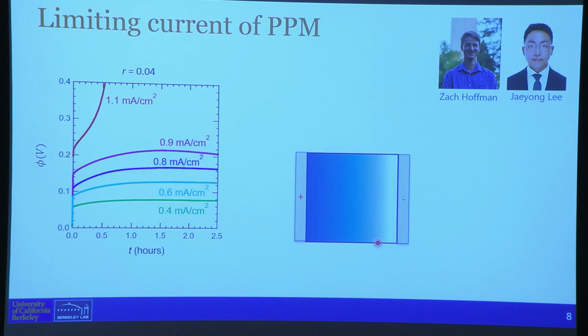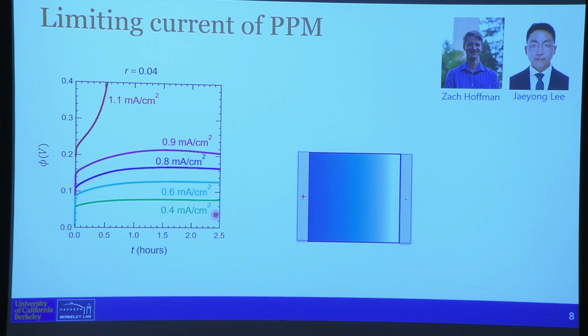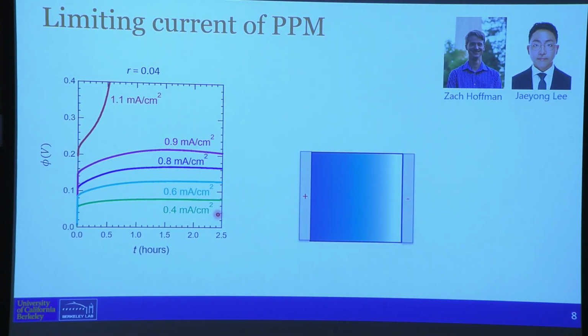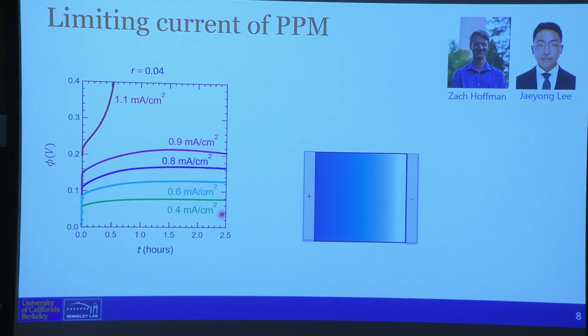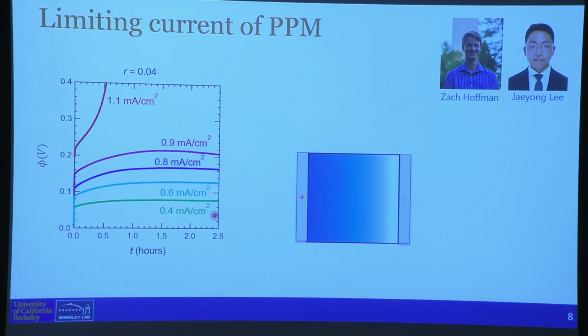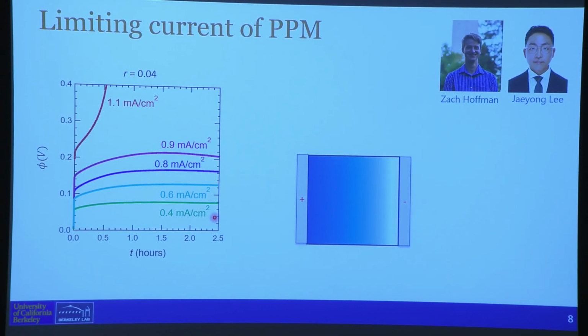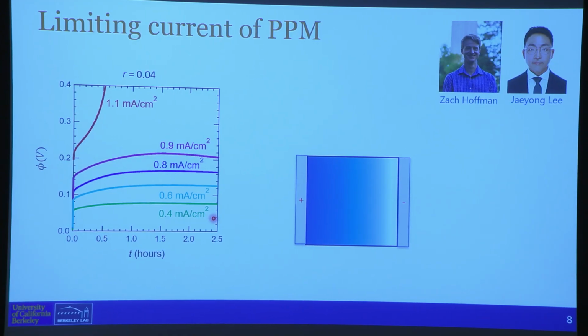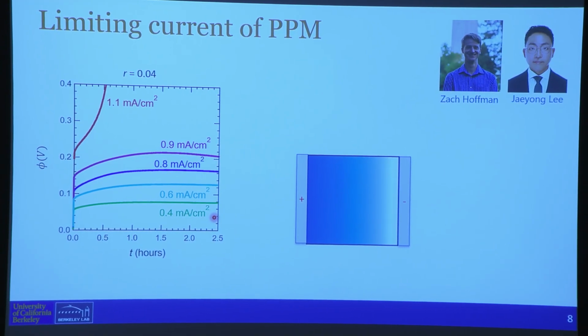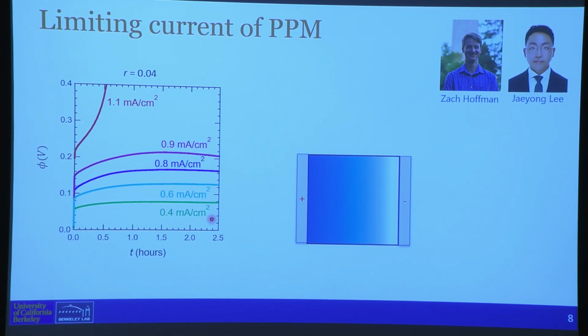In one particular experiment, you start at a low current of 0.4 milliamps per centimeter squared. By the way, all the temperatures are 90 degrees centigrade. Okay, my lab lives at 90 degrees centigrade. When you don't hear the temperature, it's always that. And that's just because at that temperature there are no interesting thermal transitions whatsoever. That it's a simple polymer, and so on and so forth.